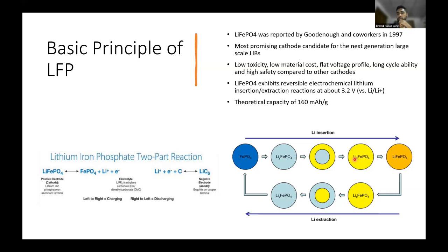When it's fully lithiated, then you need to delithiate it and extract lithium from it. Actually, there is a trick here: lithium insertion for the cathode is actually discharging, while for the anode it is charging. When we say lithium extraction, that means lithium is going out of the lithium iron phosphate. The lithium is now charging the anode, that means charging the battery. As I have told earlier, lithiation of the anode is charging, and delithiation of the anode is discharging. That is from the anode side. From the cathode side, lithium insertion, that means lithiation of the cathode, is actually discharging, and lithium extraction, that means delithiation of the cathode, is actually charging.